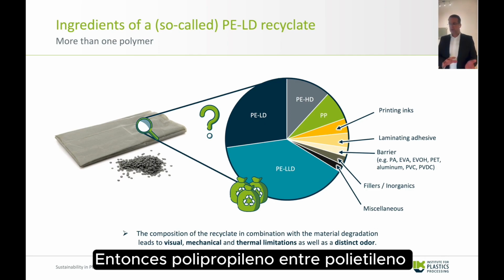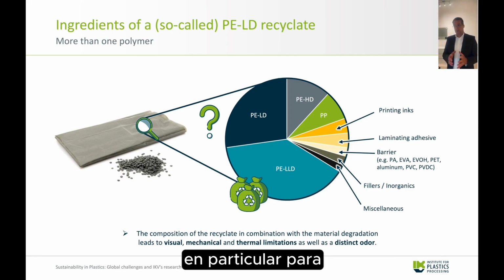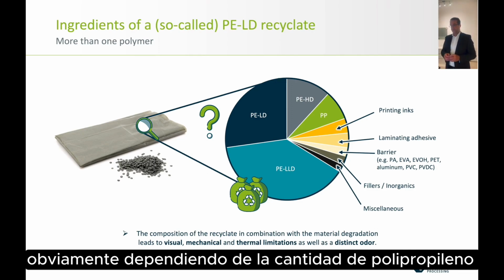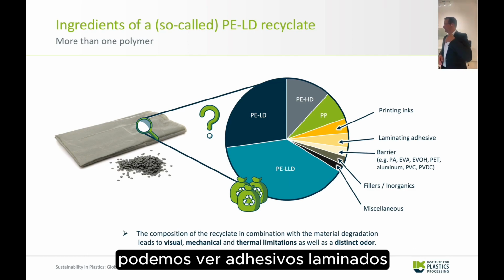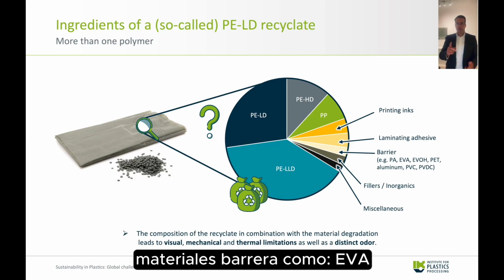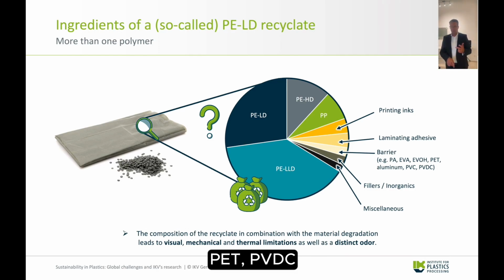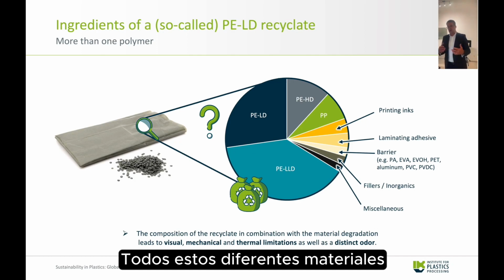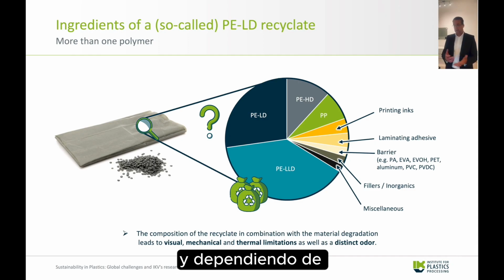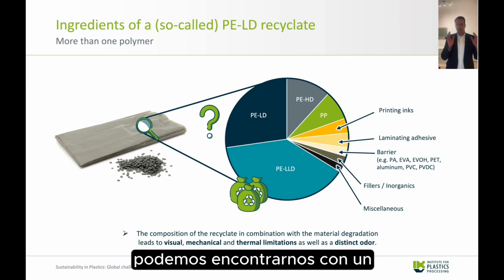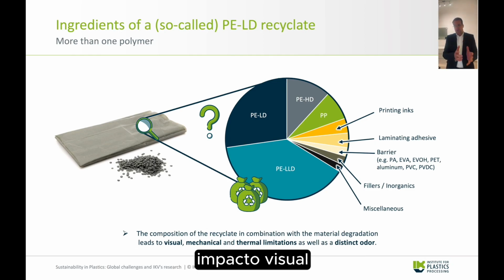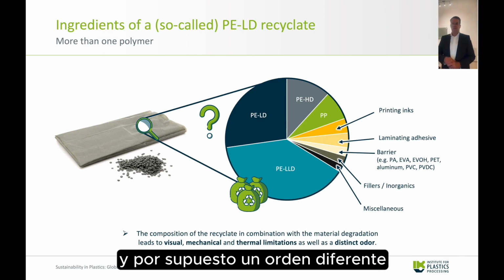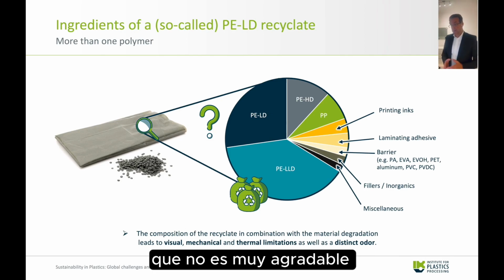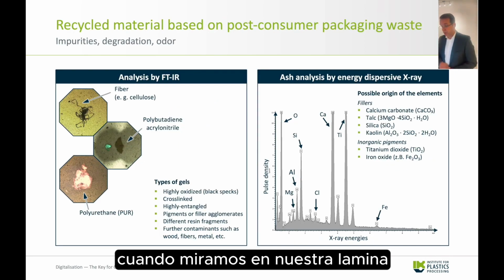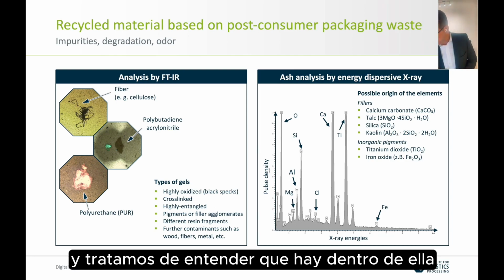So polypropylene within polyethylene, that's an issue for film production, in particular for blown film production, depending on the amount of polypropylene, of course. Then we see printing inks, we see lamination adhesives, we see barrier materials, EVA, EVOH, polyamide, PET, we see aluminum, we see wood, we see fillers, we see inorganic, all those different materials, and they are creating a mixture of material, and depending on the combination of the material, we find a lot of impact on the film, the visual impact, mechanical impact, thermal limitation, and of course also a distinct odor, which is not really nice. So let's dig a little bit deeper when we look into our film and try to understand what is inside our film.